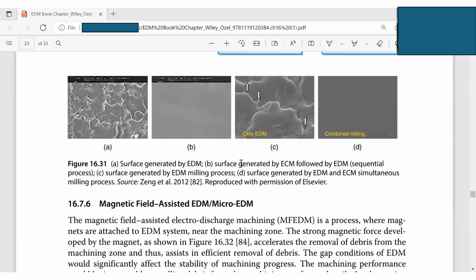And so here is a picture. The surface generated by EDM, you can see this is a kind of rough. By ECM followed by EDM, the sequential surface. So these are surfaces generated by the EDM milling process, and we talked about EDM milling already, right? Now here is EDM and ECM concurrent, simultaneous. This is very interesting. You can see very clearly.